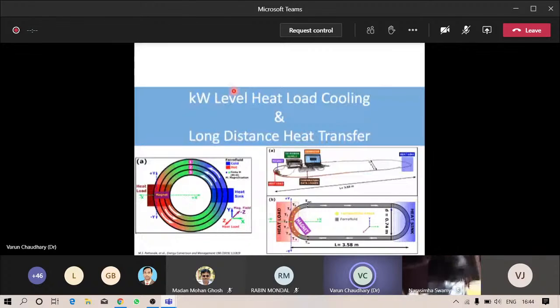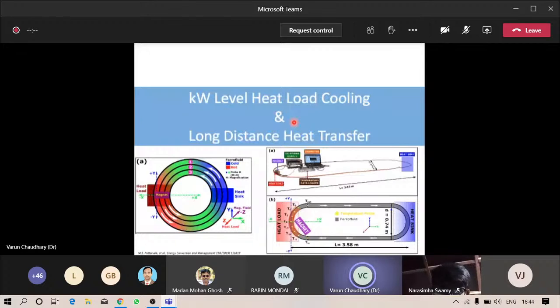So here now, the next is we wanted to check whether this technique is applicable only for below room temperature, below 100 degree centigrade applications, or it can be utilized for kilowatt level of heat load cooling. And also we tried the long distance heat transfer using this technique. So for kilowatt level heat loading, we made a device which has a multi-torus.